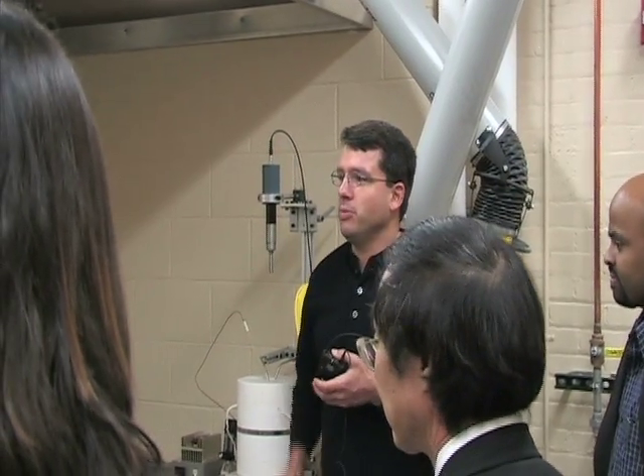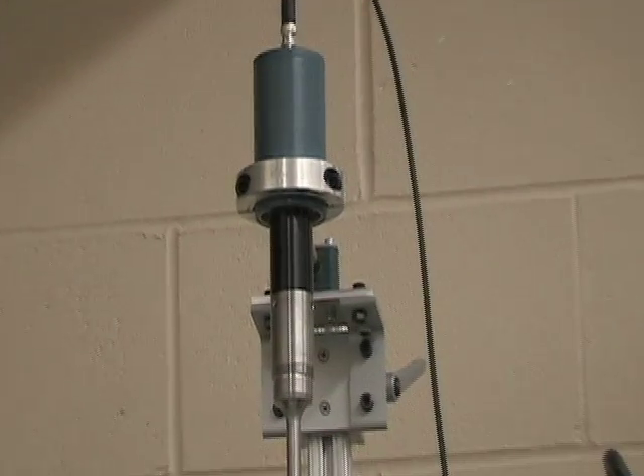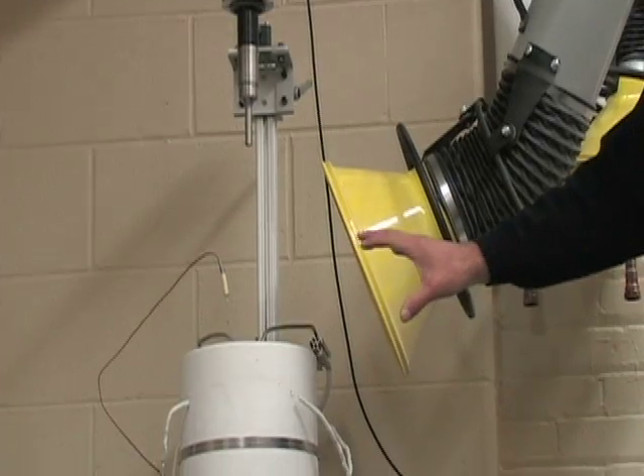So in here we work on metal matrix nanocomposites. So we're taking lightweight aluminum and magnesium alloys and pure metals and then adding nano silicon carbide or other ceramics into them to create a strong matrix or a strong composite material. And recently we found that we can double the strength of the matrix material with just a 1% volume addition of the ceramic nanoparticles. And when you compare that to conventional metal matrix composites where you put in, say, 20% of 10 micron or so size silicon carbide pieces, we get better strength enhancement, but we also don't pay a lot of the penalties that you typically see with metal matrix composites.